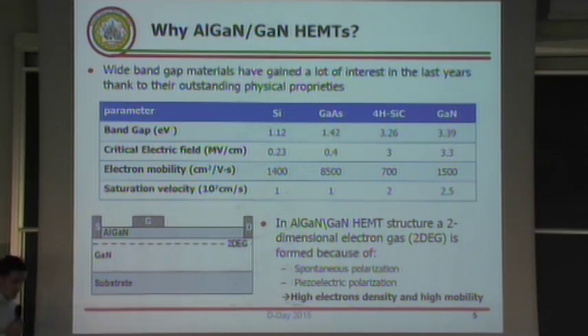On the bottom of this slide, you can see the classical AlGaN-GaN HEMT structure, where we have the heterojunction between GaN and aluminum gallium nitride, and at the interface of these two materials a two-dimensional electron gas is formed. It is formed without the use of dopants, just because of the presence of spontaneous and piezoelectric polarization. Since we don't have dopants, we have extremely high mobility in this two-dimensional electron gas, which is the channel of our device.